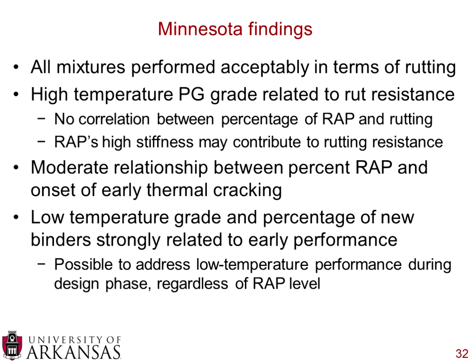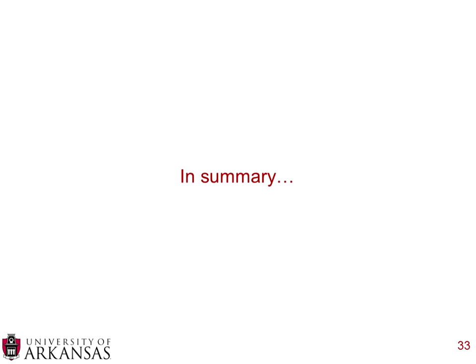And then finally, they found that the low temperature grade and percentage of new binders was strongly related to early performance. So what sort of low temperature grade? If you're in Minnesota, you're very concerned about those low temperatures. What sort of low temperature grade do you use, whether it's a minus 22, a minus 28, minus 34, or even a minus 40? That and the percentage of the new binder was related to the early performance. So they felt that it was possible to address low temperature performance during the design phase by adjusting this low temperature binder grade and adjusting the percentage of new binders, regardless of what RAP level you put in. So some good findings there from Minnesota.